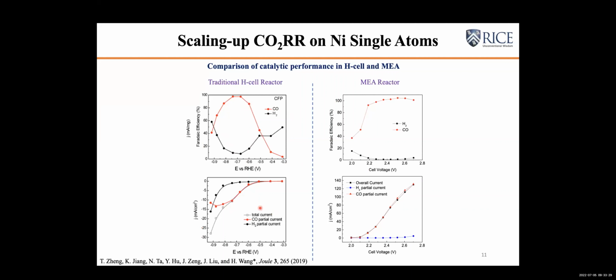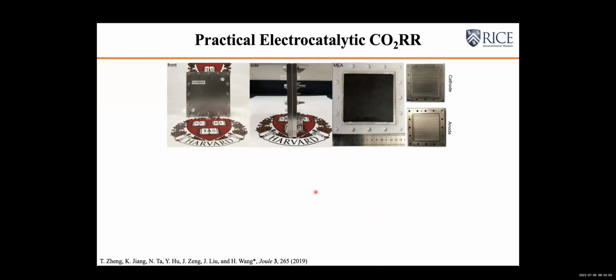reactivity. In this case, the saturated current of CO is only about 10 milliampere or so. But in this MEA reactor, we can ramp up to 100 to 200 milliampere per centimeter square while still maintaining more than 95% of CO selectivity. So in this case, it's one order of magnitude improvement compared to the H cell. And with the catalyst scaling up, the current density also can be scaled up.